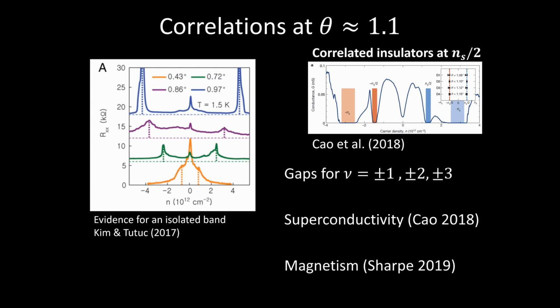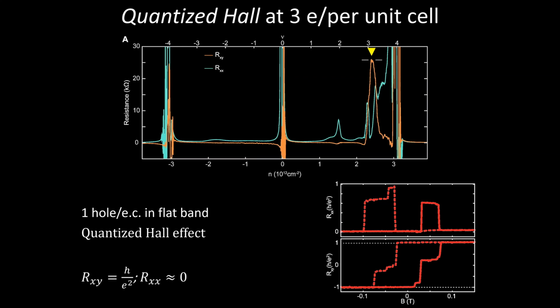It's going to show up in these systems here and there. Okay, so the first experiment that was important to talk about for this talk is that if you tune things just right, and I'll elide some of the details, you need to have twisted bilayer graphene that has the right angle, and you need that moreover to be aligned to the hexagonal boron nitride, which actually gaps out these Dirac points. And there's a conspiracy of small factors, which we chanced upon more or less at random, but have since been able to understand and reproduce to some degree.